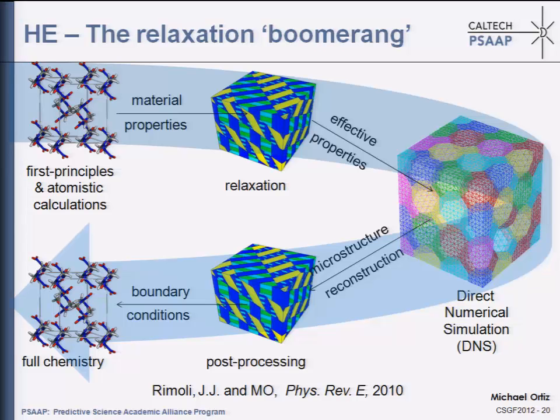So here for these materials, these are molecular crystals. There is rather little information about the behavior of these materials, for instance, the plasticity of these materials, the strength of these materials. So we filled in those gaps doing ab initio first principle calculations. When I say we, I really mean my colleague Bill Goddard and his group. And there are a number of basic properties that we computed this way, and we used them to populate the single crystal plasticity model that operates at the single crystal level.